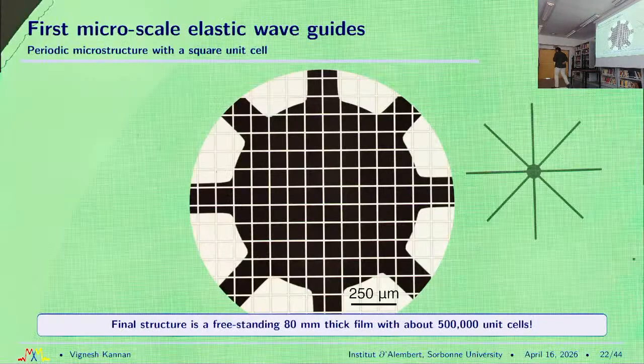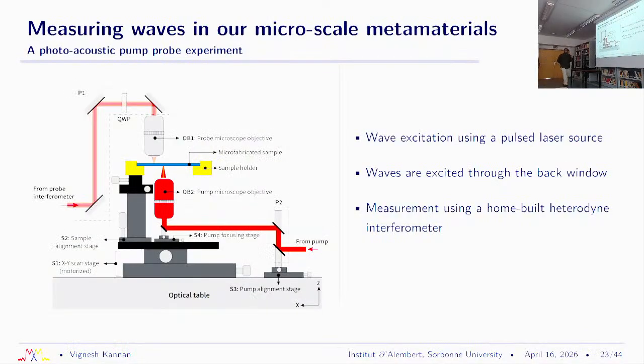So once we do this, like I said, it becomes extremely difficult or impossible to use the experimental technique we used before to actually excite waves or measure waves inside our system. So we had to go ahead and build our own experimental setup. So here I went ahead and said let's use a pump probe experimental technique where we use optics completely. So here we have a pulse laser source that comes in and excites the back of my film. That's exactly why we have the windows on the bottom surface. So we use a pulse laser, which is a 1 nanosecond infrared light source that excites the back of my film, and on the top surface we build our own interferometer. So the scanning laser Doppler vibrometer that I told you, the expensive big blue box, doesn't really work very well when you go to these very small scales. So we went ahead and said let's build our own, right?